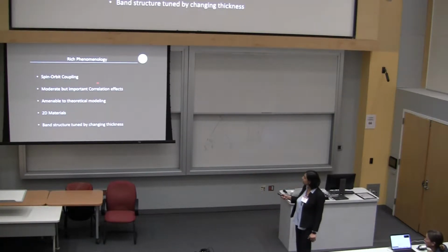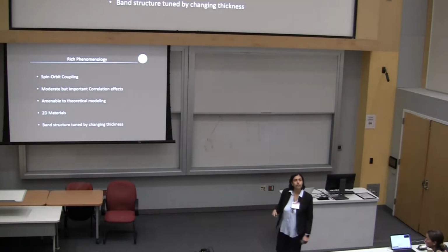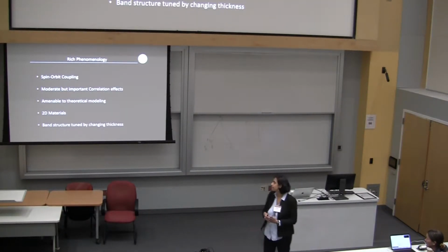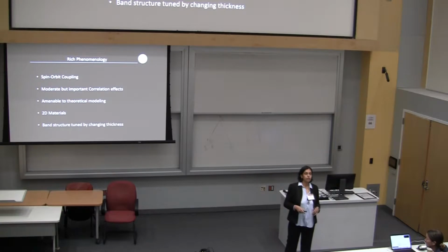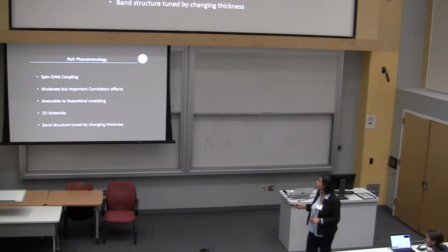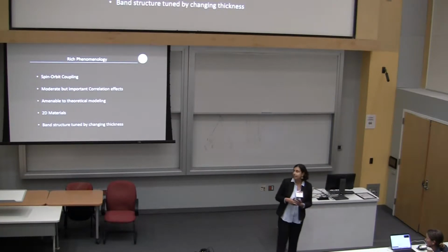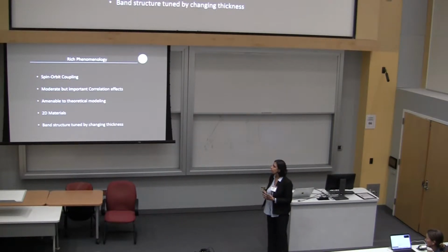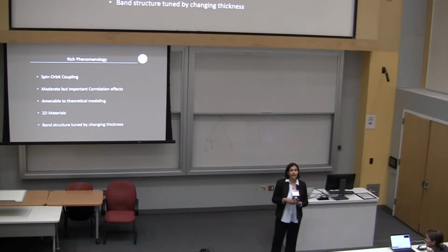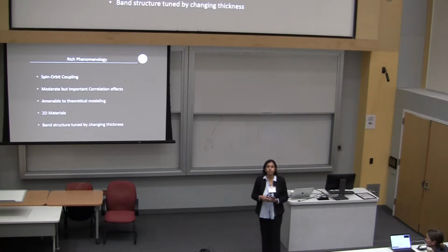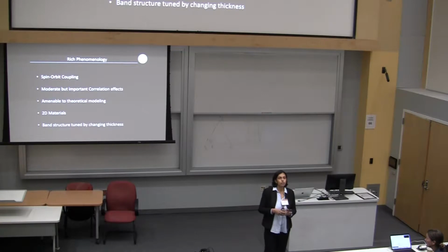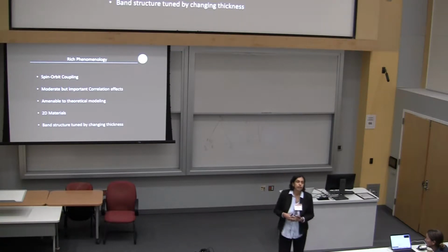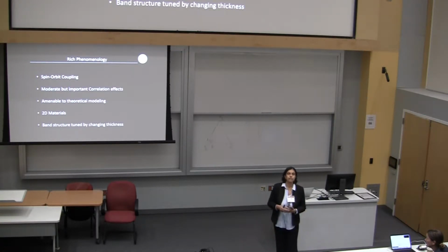You can get moderate but important correlation effects. One example would be tantalum disulfide, which is actually supposed to be a Mott insulator. The nice thing is because these are moderate, you can actually model these theoretically. The nice thing also is that many of these materials are layered 2D materials, and because of their 2D nature, you can cleave them repeatedly and make devices on monolayers and bilayers. They're also amenable to thin film growth.